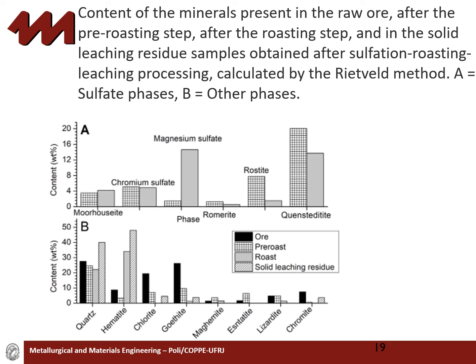Apparently, the quartz content increased in the solid leaching residue. However, after calculating the mass of this phase, it was observed that the amount did not vary significantly at any step of the process, except for the pre-roasting step. In this step, a high value for the quartz mass was found. Probably, this value was overestimated from the quantification.